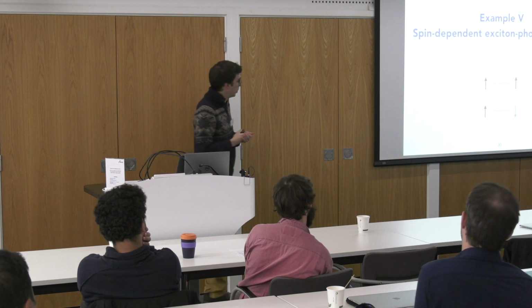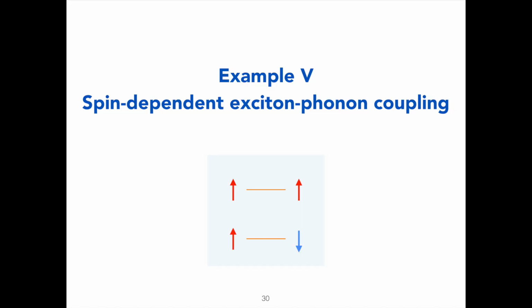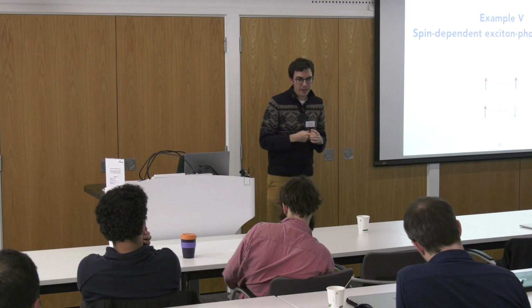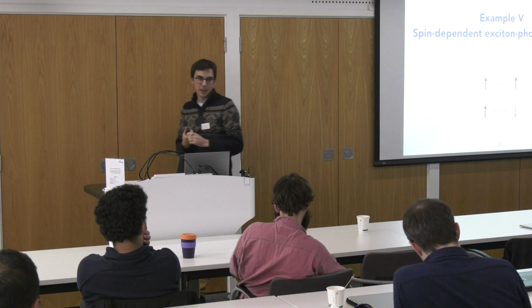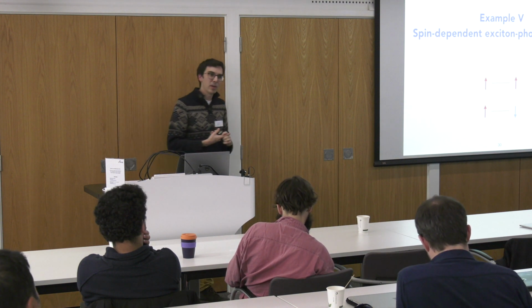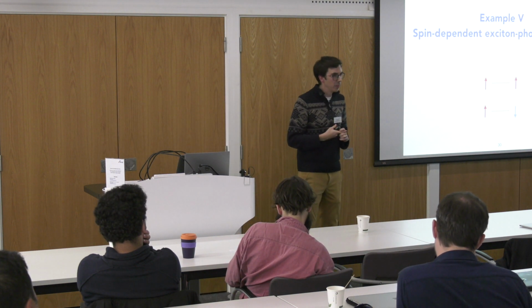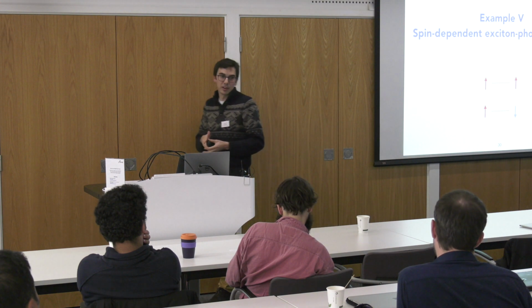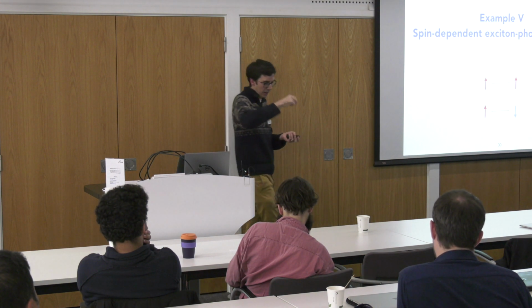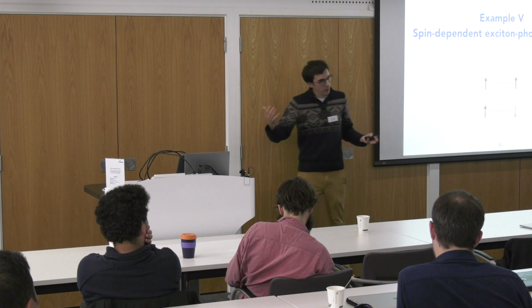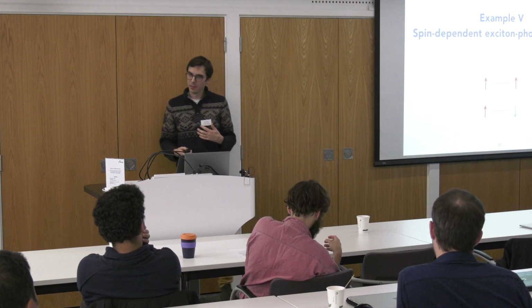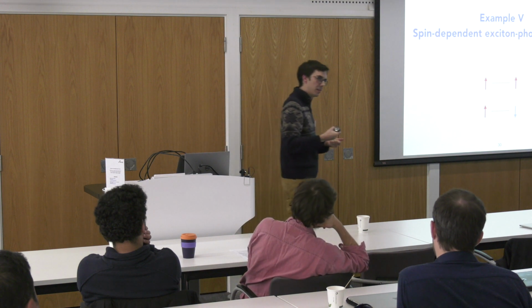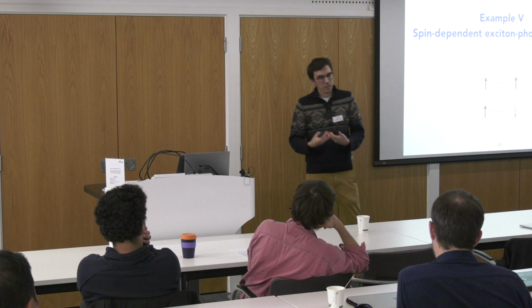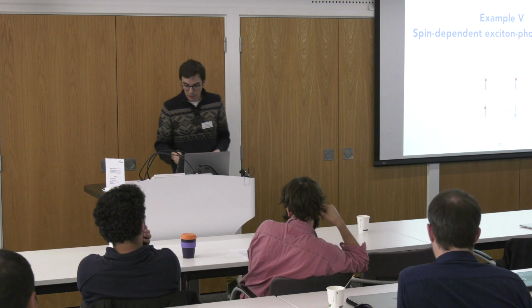So the final example that I want to look at is again looking at excitons and the interaction of excitons with dynamic disorder. And in this particular case, we're going to look at another case where excitons play a fundamental role, and that's in organic materials. So in inorganic materials, exciton binding energies are relatively small because the screening is very large, and therefore the electron-hole interaction is largely screened, so they're weakly bound. But in organic materials, the screening is much weaker, and therefore the electron-hole interaction is much stronger, and you can form strongly bound excitons.